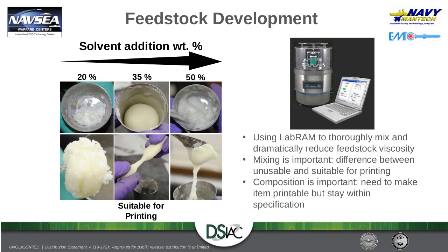So that little study that we did was just keeping the composition of the final product the same whilst having the affordability and flexibility of changing the processing by way of adding a certain amount of solvent, and that's what you see there. We start off with a low amount of 20% all the way up to 50%, and the high extremes, 20 and 50%, were either too dry and not really supportive of good mixing, or just ended up being overly mixed and having more than what you need of solvent, whereby it wouldn't be amenable to 3D printing.